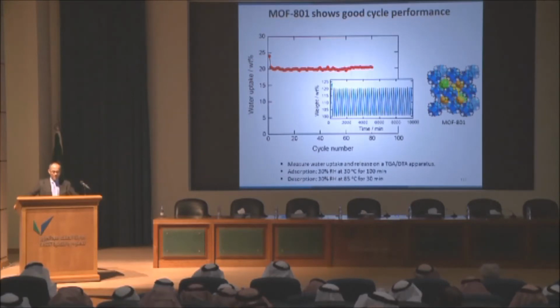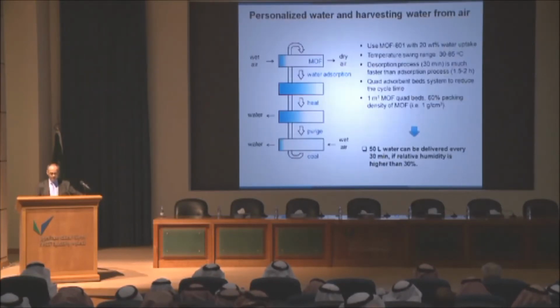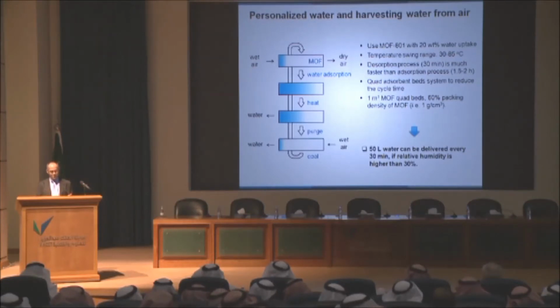And here's a MOF we call MOF 801. And this is the uptake. It shows the uptake and release of water. 80 cycles, absolutely no effect on the efficiency of the material. We did a rough calculation that if this material takes up 20% water, we have a material that takes double that, but we did the calculation for this one because we can make it in kilogram quantities very quickly. But at 20% uptake, this material can deliver 50 liters of water every 30 minutes, okay? And that's for a system that has 1 meter cubed of MOF, okay?